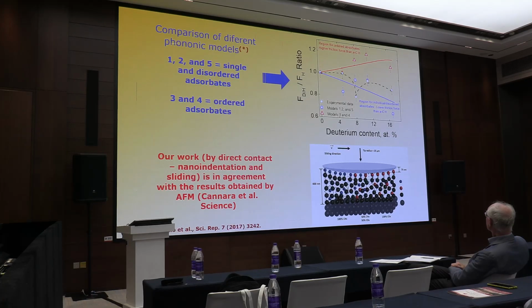When we use these models with our data, you can see that these three models are in agreement with our data. What does it mean? That the carbon thin film with hydrogen on the interior is not organized. It's amorphous. DLC is mostly amorphous. There is tetrahedral with some order, but in our case, our DLC is amorphous, disordered. So we have an agreement of the structure, because it's amorphous, with the model of disordered adsorbate, and all are in agreement.